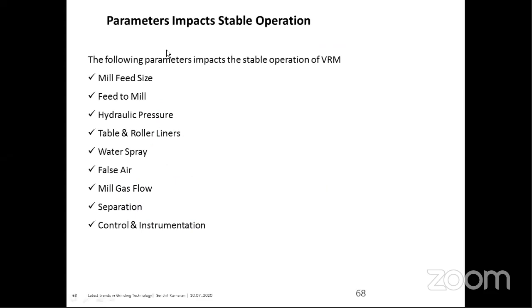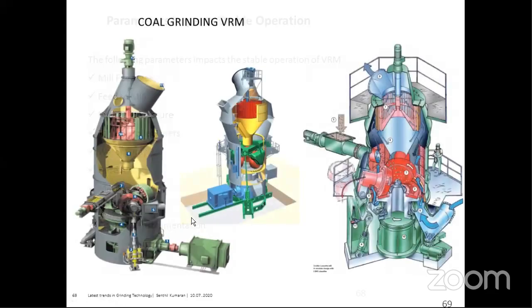So the stable operation parameters are feed size, feed to mill, hydraulic pressure, liners, water spray, false air, gas flow, separation, and instrumentation. Then there is the coal grinding VRM. In the raw grinding VRM we grind the raw material, which is limestone powder. Limestone powder is typically an inert material, so it is not an issue. For coal grinding, when we grind the coal finer and heat it up too much, the chances of explosions are high.